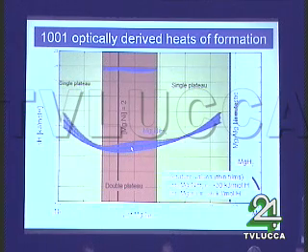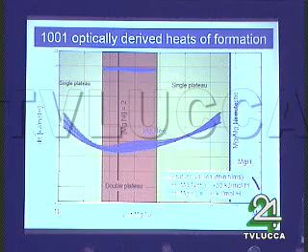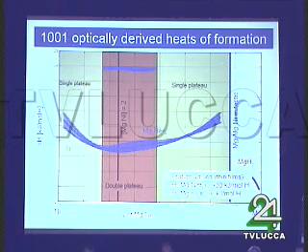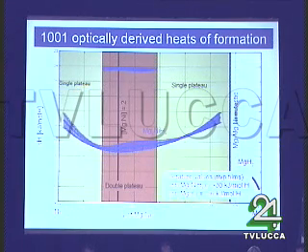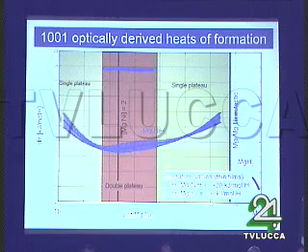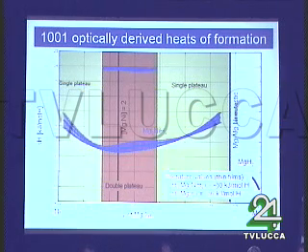Maybe also important is to see the values. We are in kilojoule per mole H, okay? So we are around minus 30 here. And if you look at literature values for thin films, this is exactly what has been reported in the literature.